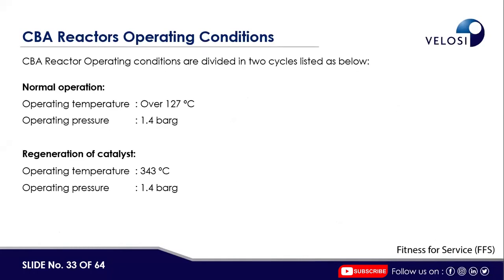In normal operation, when we say low temperature, it is not so low: it's 127 degrees Celsius, and the operating pressure is 1.4 bar G. For regeneration of the catalyst, the operating temperature is 343, which is the big difference between both, with an operating pressure of 1.4. If you see the temperature ranging between 127 to 343, it basically created thermal expansion issues as well.